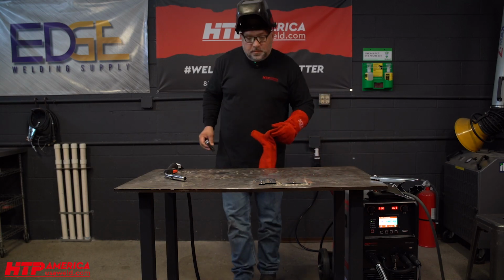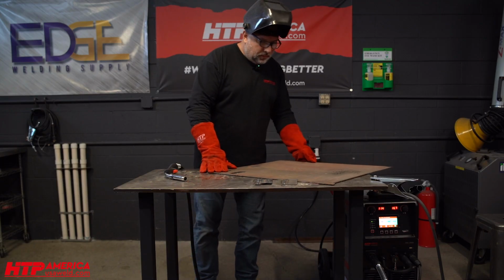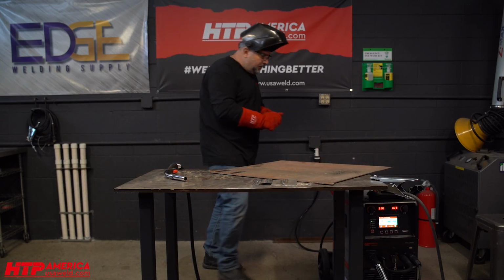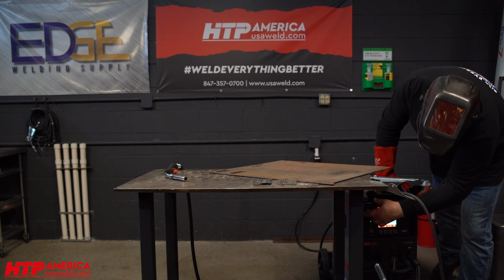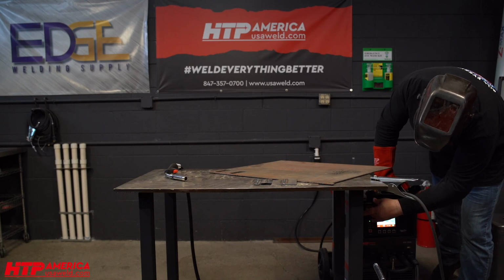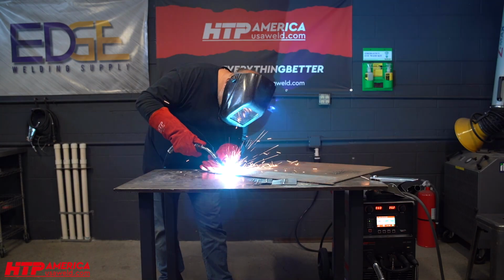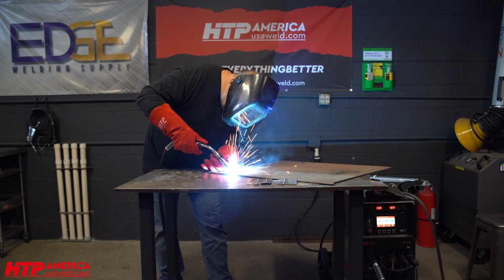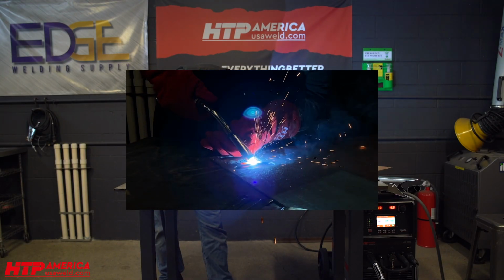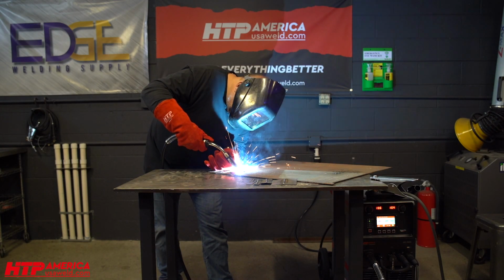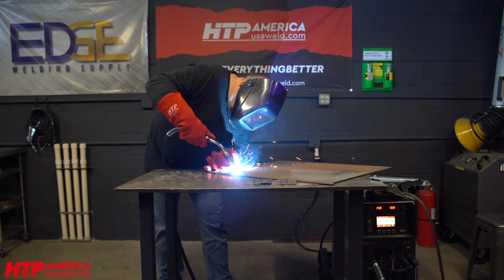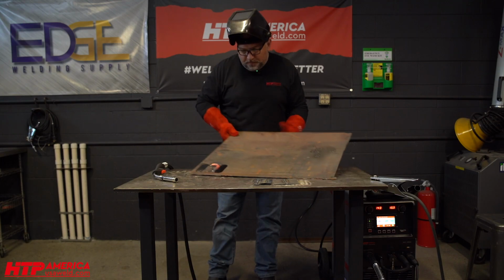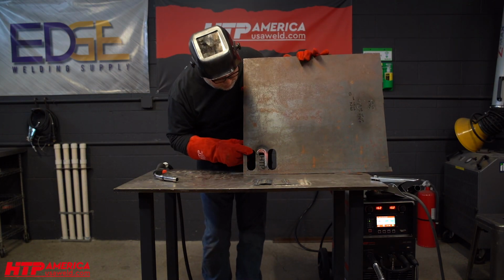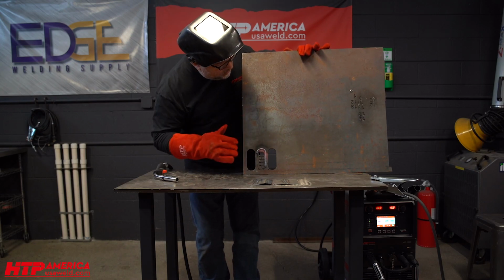Now let's bump it up to 1/8 inch. So this one here is actually 10 gauge, I believe, 135 thousandths thick. And I go right to the 10 gauge setting. Now would you look at this? Absolutely no spatter, no BBs flying around. The arc never stopped on this nice, crusty, rusty material.